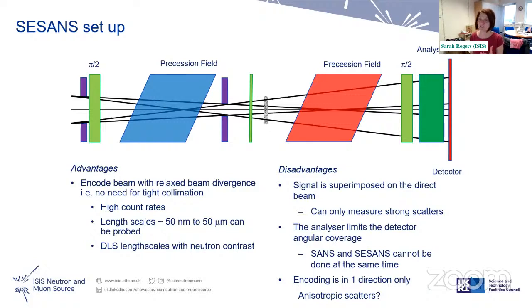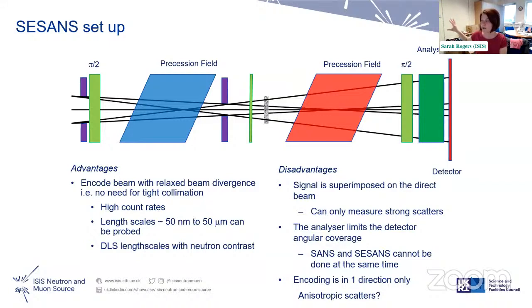There are obviously disadvantages to this, otherwise we'd do it all the time. Those disadvantages are that the signal is superimposed on the direct beam that we're hiding on the SANS detector. So your sample has to scatter quite strongly to distinguish it from the direct beam. We also have to have an analyzer in place, which impacts the angular coverage we can have on the detectors.